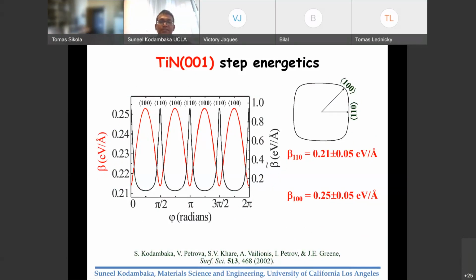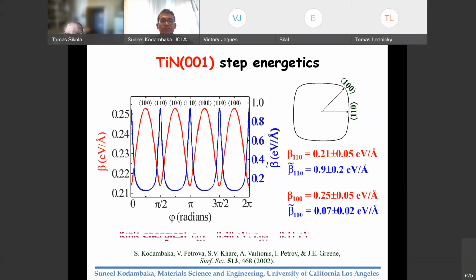And if you recall the step fluctuations that you saw in the video, the steps that fluctuated more vigorously, those are the steps with low stiffness. You can think of them as guitar strings that are tight versus a bit loose. The ones that are loose vibrate more. This is essentially the same thing. So the steps with low stiffness, they fluctuate more. The steps with high stiffness, they are the stable steps, and they do not fluctuate as much. And so we can get the step formation energies and step stiffnesses. And from the step stiffnesses, we can also extract kink formation energies. But however, these depend on a particular model that you choose. And so anyway, all this type of information one can obtain by doing scanning tunneling microscopy and watching the dynamics happening on surfaces.